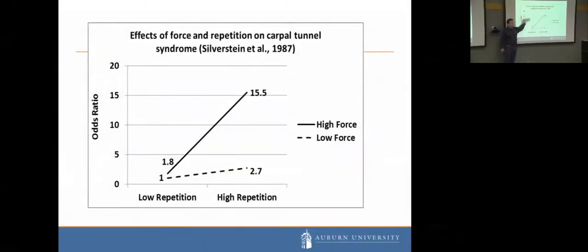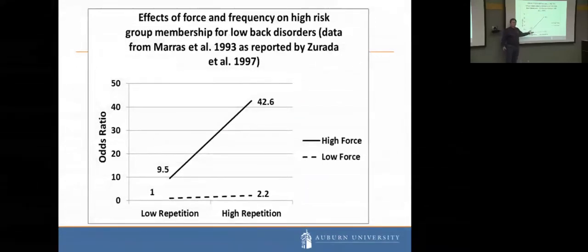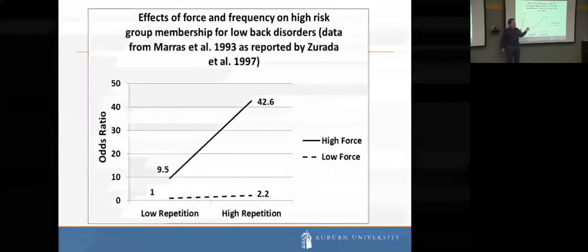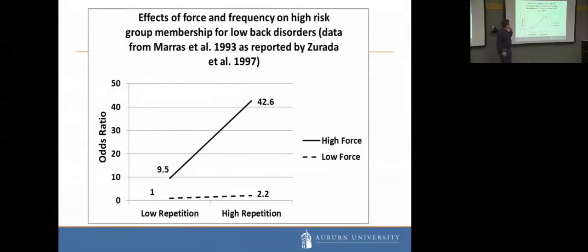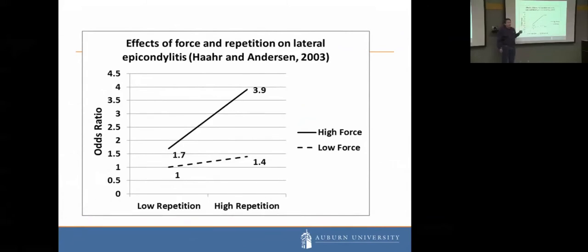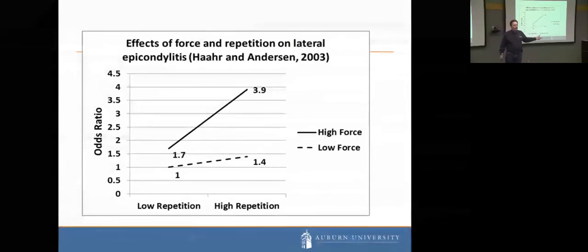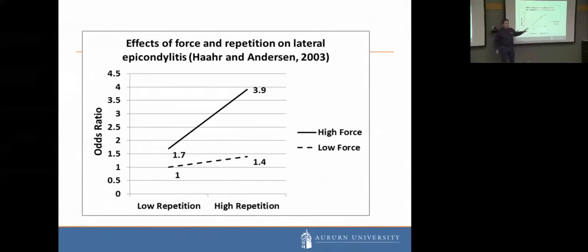This is also by Silverstein, kind of in the same group, doing a study on carpal tunnel syndrome. And we see the same type of pattern happening there. We actually were able to get the data from this study. They actually didn't look as to whether there was a force repetition interaction with this one. But this is for low back injuries. And, again, we see the same type of pattern. This is for lateral epicondylitis in a study by Haahr and Andersen in 2003. And you can see the pattern that's occurring here. So this pattern is really indicative of something happening with an exponential curve like that. It really makes sense that it's a fatigue failure process.